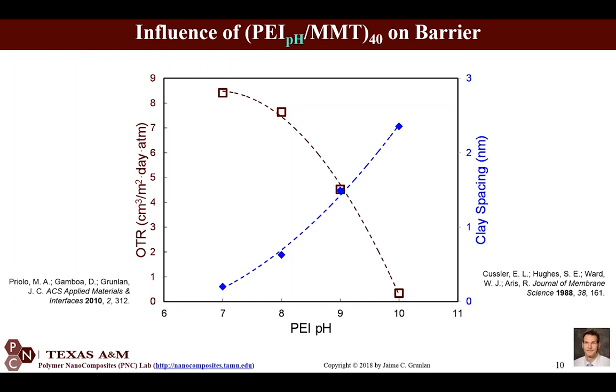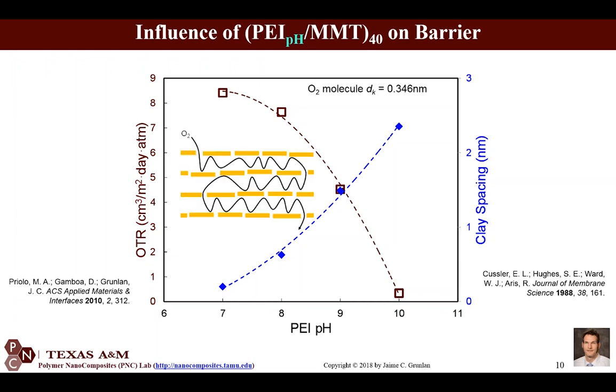and I'm actually influencing the clay spacing with the pH of the PEI being used. If I increase the pH of PEI, I'm decreasing its charge density. That means it's a weak polyelectrolyte, and it deposits more thickly because it's not repelling itself during the layer by layer assembly. And so we can really dial in a gas barrier, in this case an oxygen barrier, because we're building this very intricate nano brick wall structure, as we call it, and you have a very tortuous path for any gas molecule trying to get through. Even hydrogen barrier can be created in this fashion.